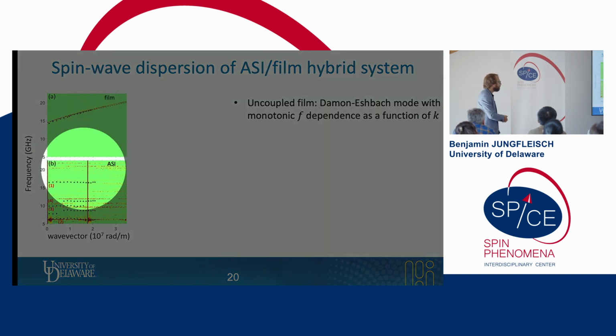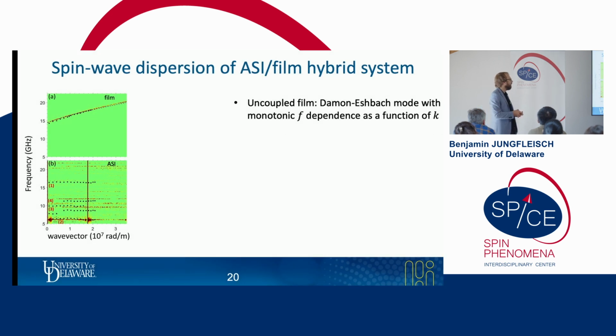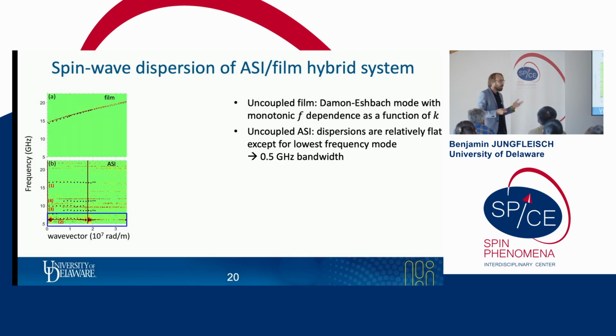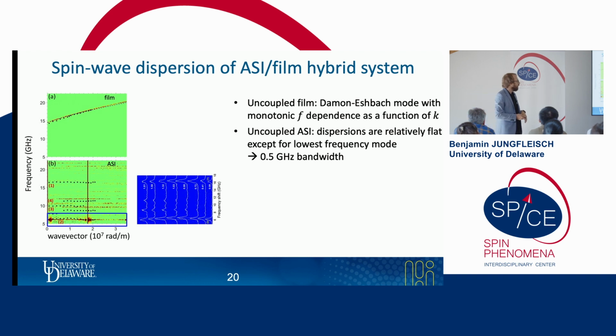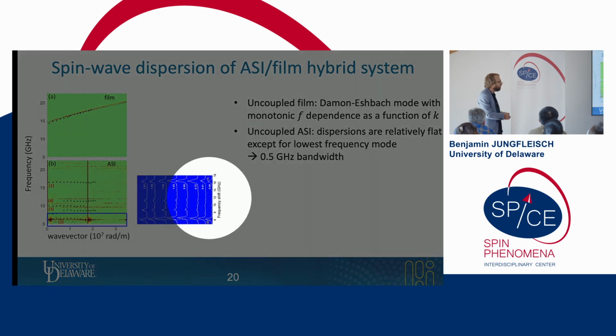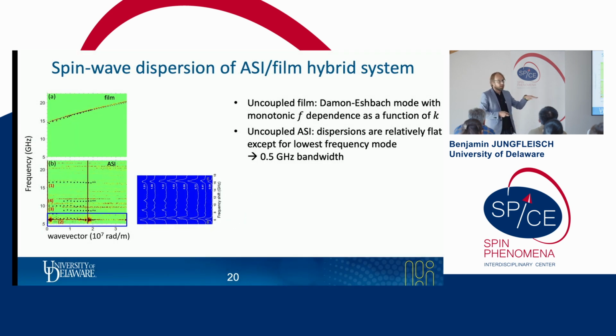On the bottom, I'm showing here the artificial spin ice system. And surprisingly, the modes are rather flat. There is only one mode, and that is the lowest frequency mode that exhibits some kind of variation in frequency. And I'm going to show you this in a little different way. So these are the spectra at different in-plane angles of incidence, corresponding to different wave vectors. And if you look now at this lowest frequency mode, you can see that there is a bandwidth of about 0.5 gigahertz.